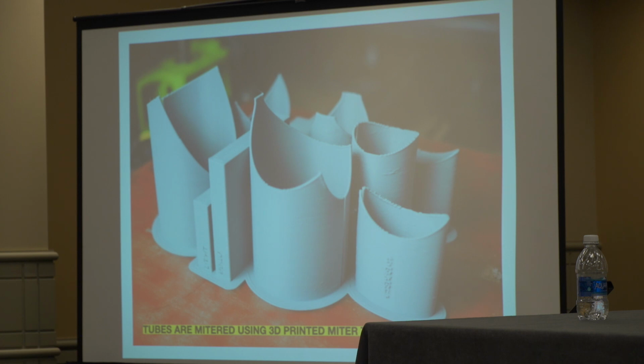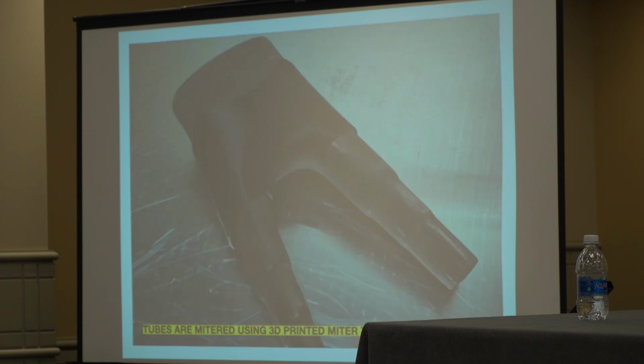Once the tubes are made, they're mitered. And I use 3D printed, why not, right? I use 3D printed mitering templates. Some people use paper templates. The reason I use 3D printed miter templates is so I can get alignment of those templates along the tube. If you use a paper template, there's a possibility that you could introduce a little bit of twist as you're putting that template on the tube. So I've got these flats on the miter guides themselves, and I can ensure that they're perfectly aligned along the length of the tube when I place them. These get extracted from the 3D model of the bike, and I know exactly where to place them on the tube so that everything fits together later.